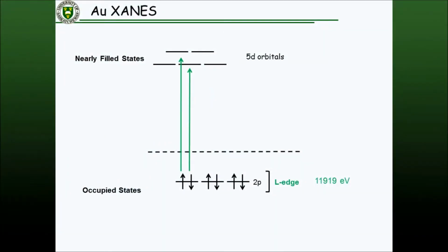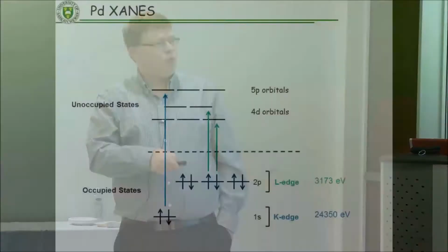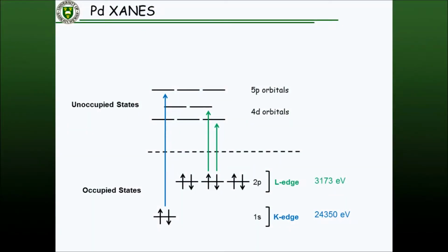So we have two major experiments that we can do with the CLS on these systems. Gold is one. The L edge, for example, in gold, 2p to 5d transitions at the edge. Most of the gold particles have d10 environments, in which case the spectroscopy at the edge is not particularly informative. But we can also look at the palladium, and this is where things get a lot more interesting. We can look at either the K edge of palladium, which is the 1s to effectively 5p transition, or we can look at lower energy, which is the L edges, which are the 2p to 4d transitions. Those are really interesting because they probe the 4d occupancy of the palladium, and so we're talking about different palladium oxidation states, palladium-2 versus palladium-0. We'll see a difference in the intensity of the transition at the edge, depending on what the oxidation state of the palladium is.